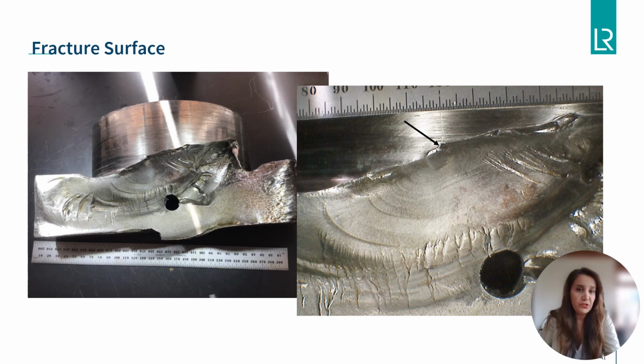Fatigue cracks generally initiate in areas of highest stress concentration. Sharp cracks, defects, grooves, and changing sections can often act as stress concentrators, which can increase the probability of crack initiation. In the immediate areas of these stress concentrators, the effective stress is greatly increased. The initiation site was located approximately 15 to 20 millimeters from the main bearing journal to crank web fillet radius. Now let's take a look at other features.